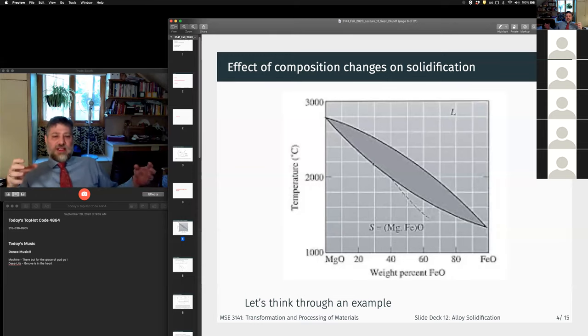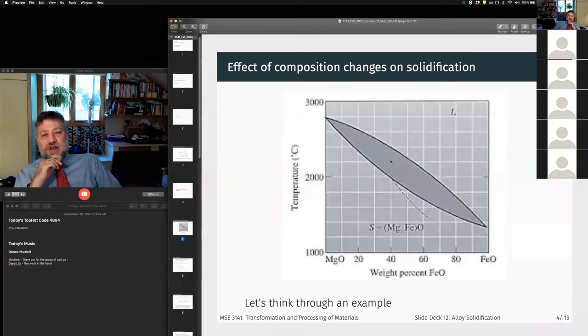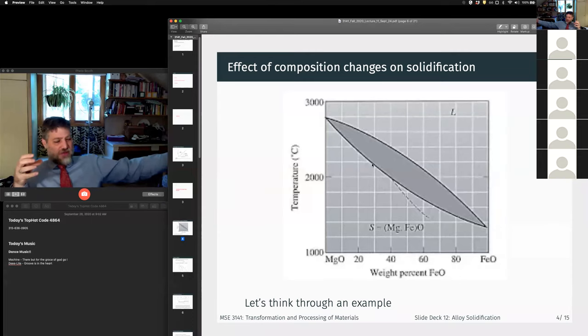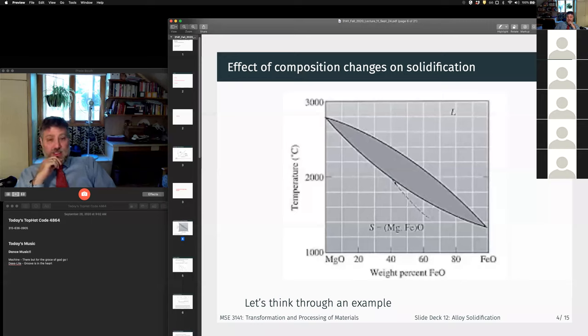So the bulk solid composition, the average solid composition, would be homogeneous at the alloy composition, right? It's only when we solidify faster than diffusion happens that we get the composition gradient in our solid. If we froze this really quickly, and we did a directional solidification of a bar, so we started freezing from one end and froze out to the other, one end of the bar would have a composition out here, and the other end of the bar would have a composition out here.